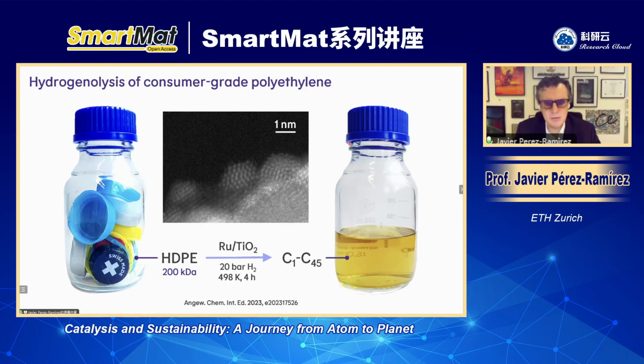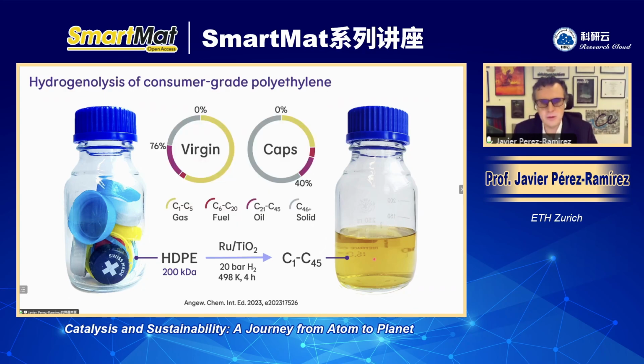And I want to show you here one example that we have published very recently in Angewandte Chemie, where we have used very tiny nanoparticles of ruthenium supported on titanium oxide to convert high-density polyethylene with a very high molecular weight. This is consumer-grade polyethylene caps, actually, to convert it into liquid products, using hydrogenolysis chemistry. And so here it's just to show you that you could make pretty interesting products out of waste plastic, tuning the nanostructure of the catalyst, in this case, ruthenium nanoparticles.